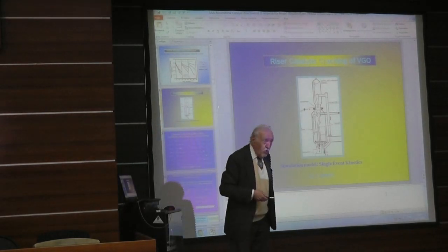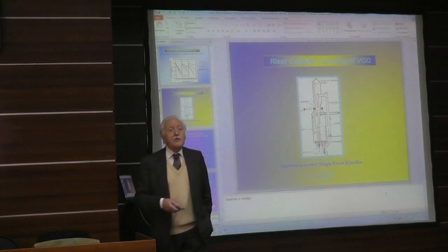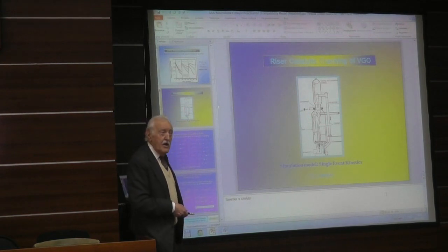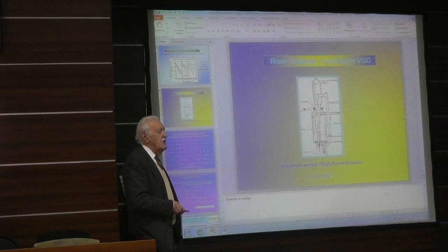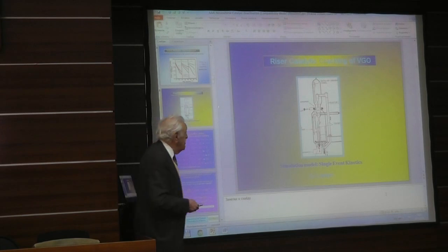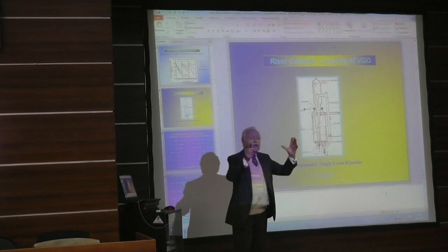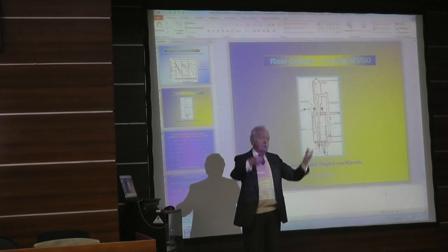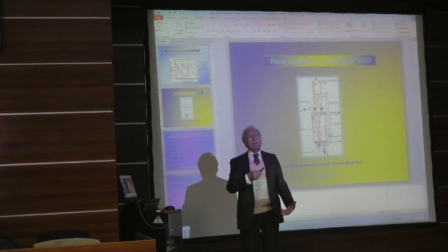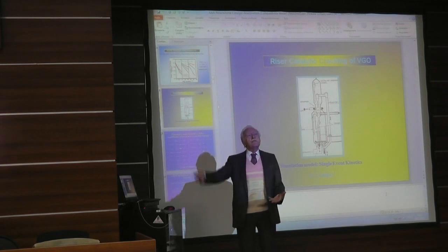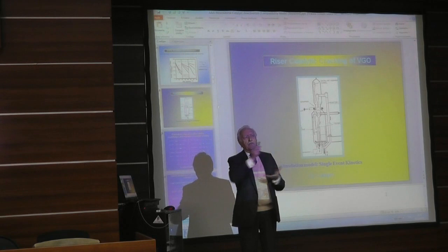Then, during the World War, the U.S. government encouraged companies like Exxon and engineering companies like Kellogg to cooperate and design something that would be more efficient for cat cracking than the Houdry fixed bed system. In 1942, Kellogg and Exxon developed the fluidized bed technology, whereby in one bed you have the reactions and the catalyst deactivates by coke formation. You circulate that into the regenerator, you inject air, you burn off the coke, and you recycle the catalyst to the reactor.